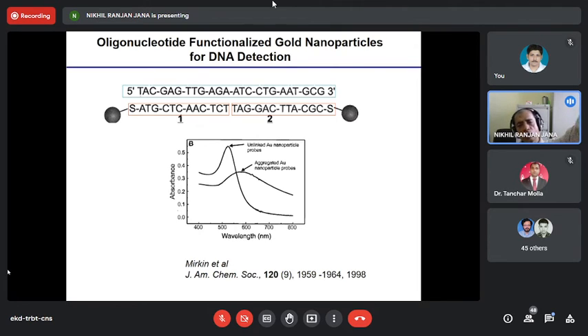Once your target nucleotide is mixed with the two sets of gold reagents, the gold colloid color will change because of its complementary sequence, they interact with each other, and that interaction will lead to particle-particle aggregation. Gold nanoparticle aggregation will lead to color change. This color change can be used for detection of your oligonucleotide. This is a very powerful approach. We can detect single oligonucleotide mismatch.